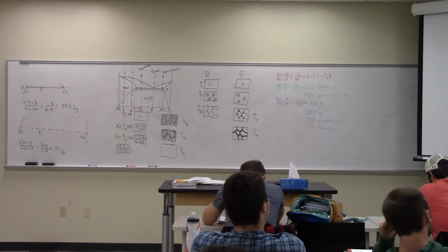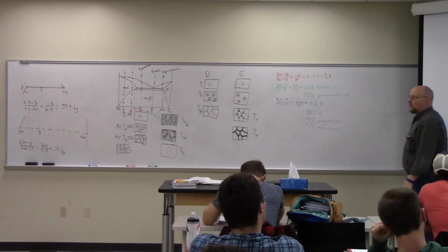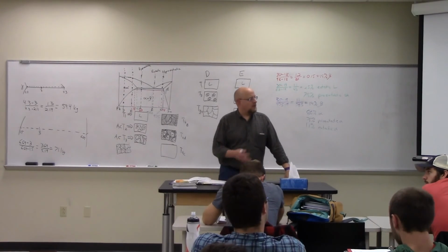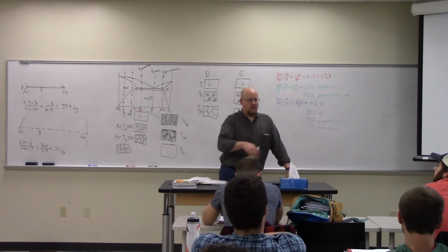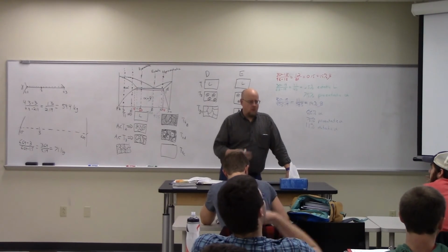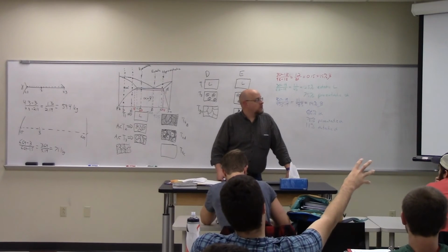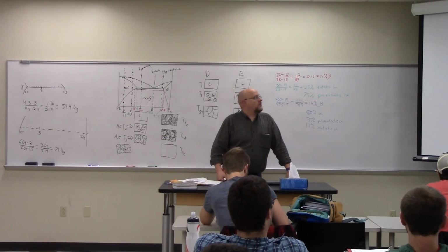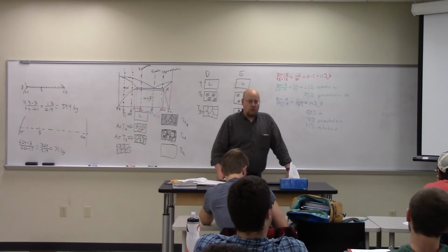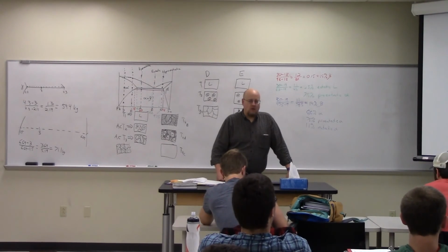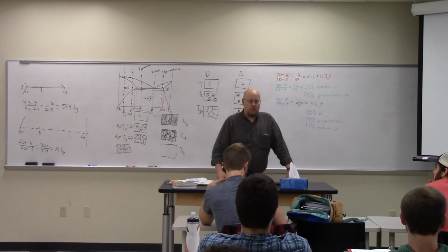Will cementite ever not be eutectic? Not in the part we care about. We don't work on the right-hand side of it. Oh, I see. If you go on the right-hand side, I thought you meant for the 4.3% composition. If you go to the right of 4.3, then you can have cementite that is not eutectic. So you can have non-eutectic cementite above 4.3%.